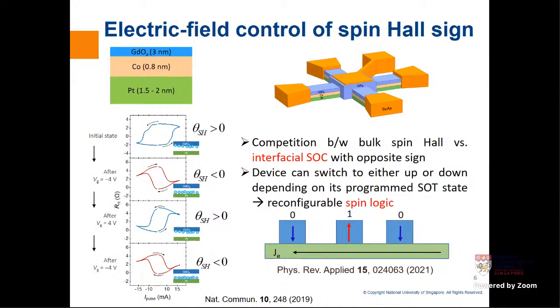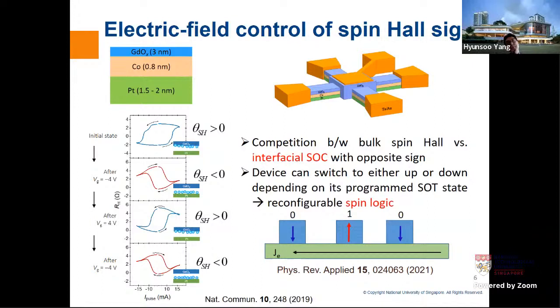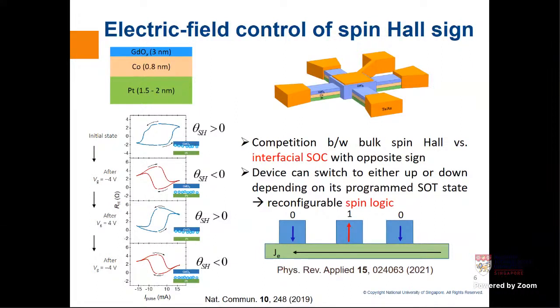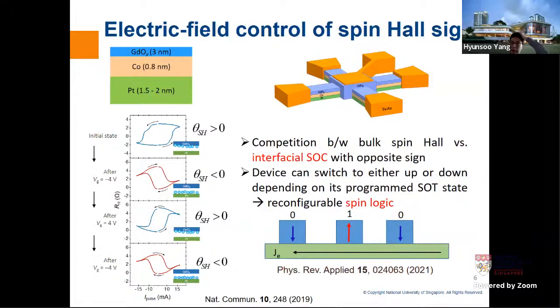So when you're studying the 10 micrometer device and the 400 nanometer device, what did you see as the difference in the domain propagation or domain motion? Sure. So our speculation is, if the device is so large, then you have basically an averaging effect. But if the device is getting smaller and smaller, then the exchange bias is maybe not very uniform, because typically this exchange bias is the interfacial uncompensated spin phenomenon, and we do not have a homogeneous uncompensated spin across the whole uniform area. It's impossible.